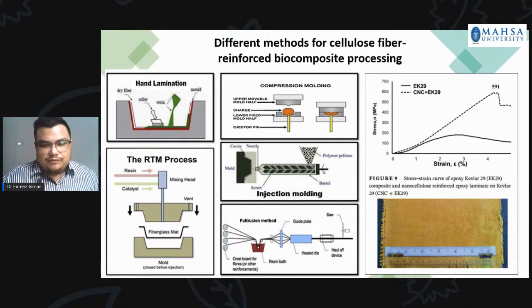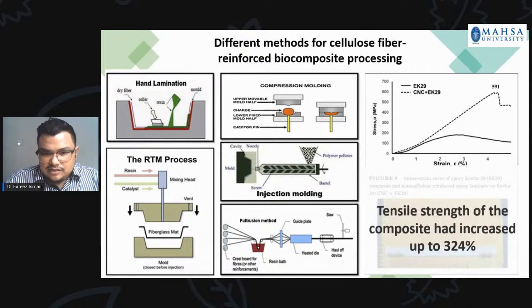So in my paper on the rice straw nanocellulose, at the end we actually tried to measure the mechanical strength of this nanocellulose reinforced epoxy composite. We call it epoxy laminate using Kevlar as the base, to see whether there is any improvement in the strength, or the tensile strength. And what we found is the tensile strength of the composite had increased up to 3 times. And the elasticity of this composite has also increased by 3 times, when compared to the Kevlar alone.